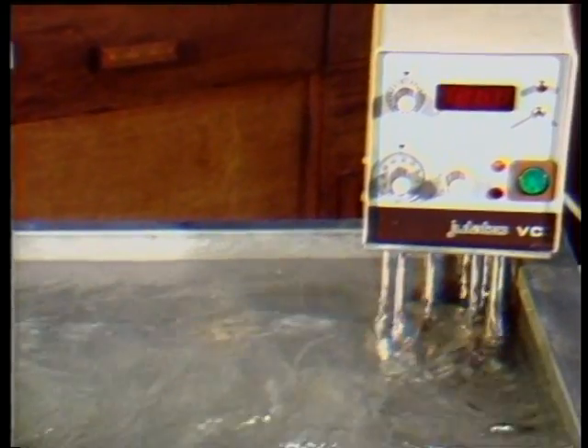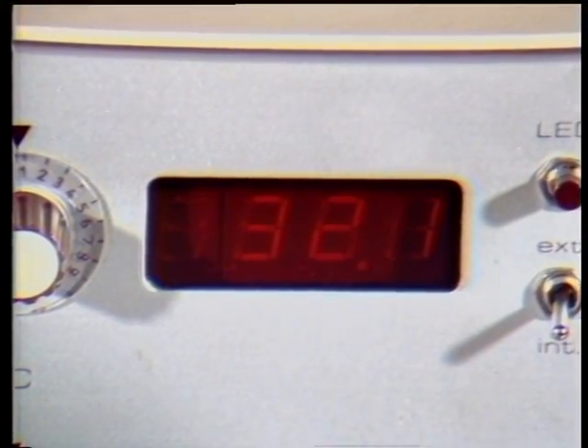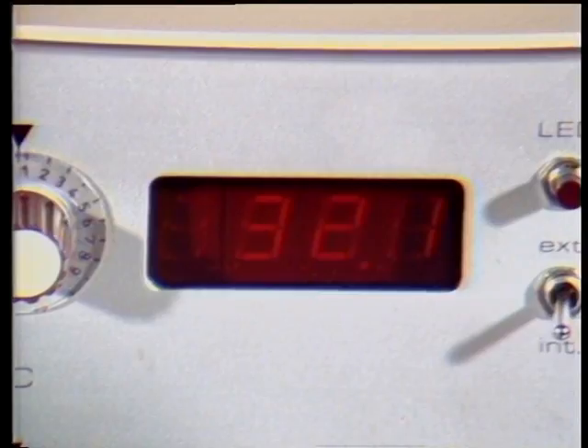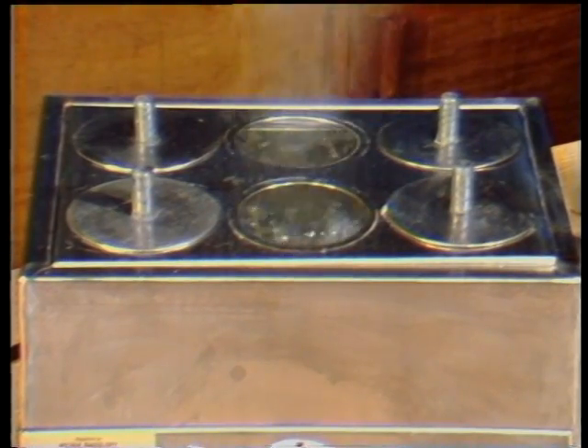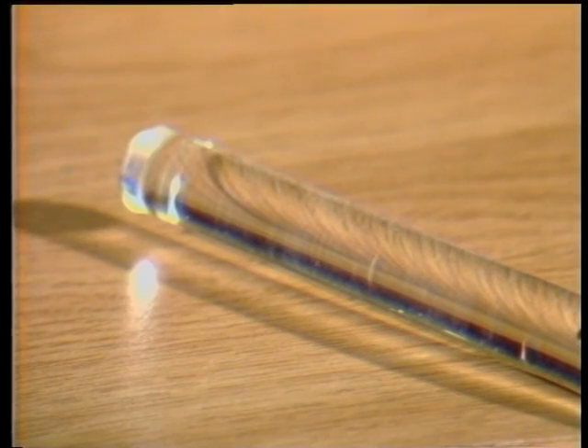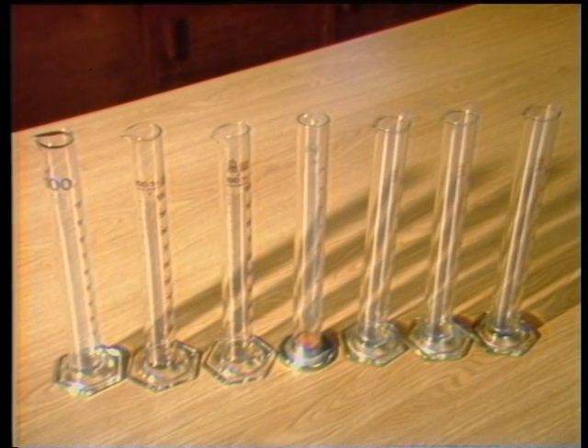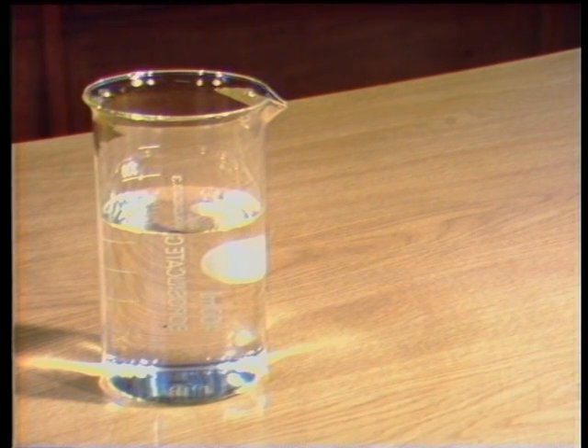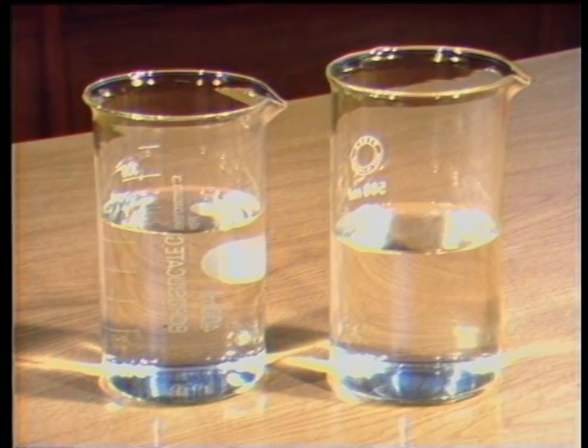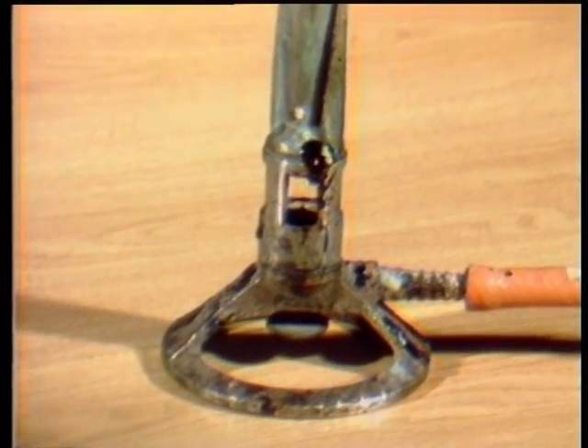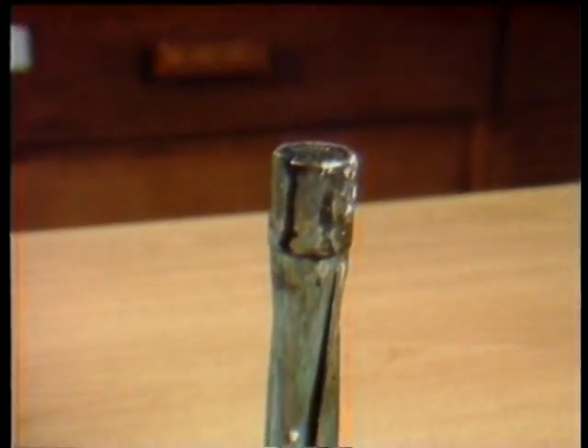A water bath at 32 degrees Celsius. A water bath at 100 degrees Celsius. A glass rod. 7 100 milliliter measuring cylinders. Heptane and xylene. And a gas burner or hot plate.